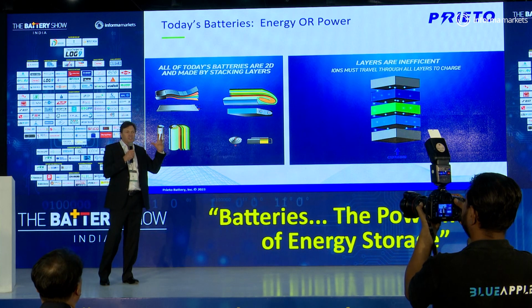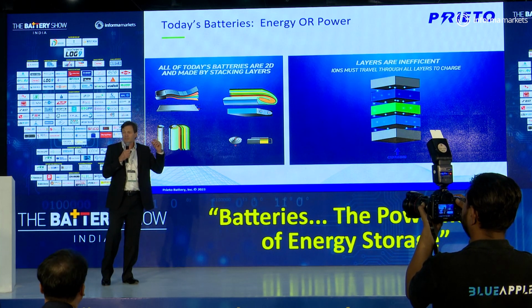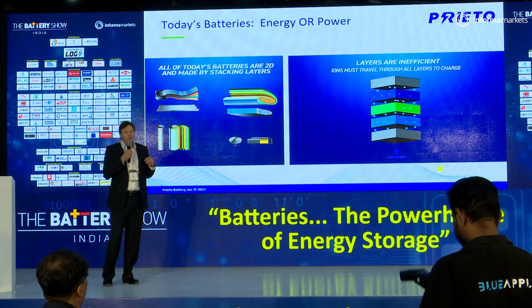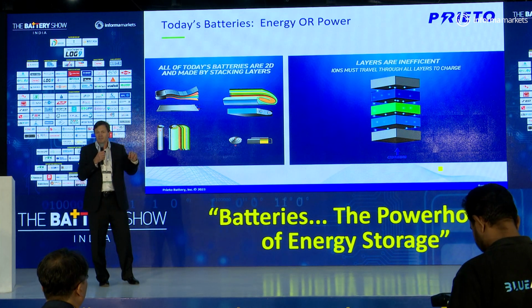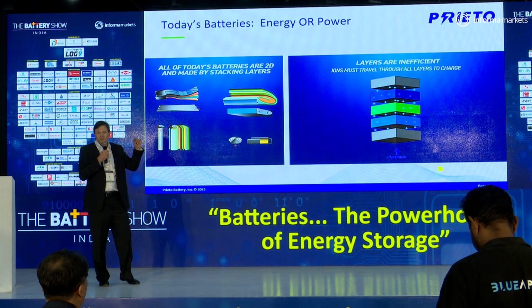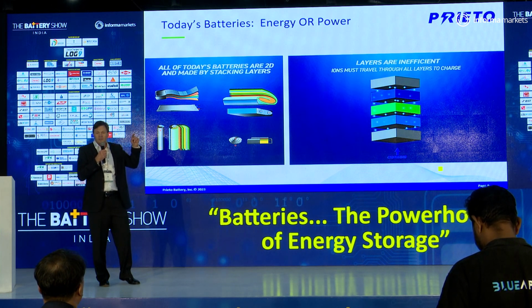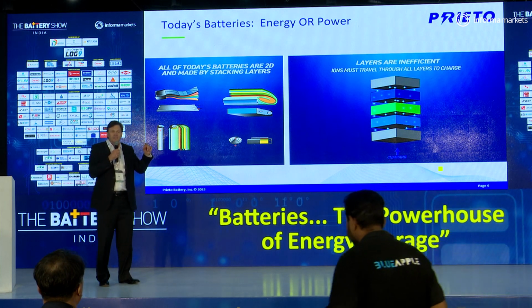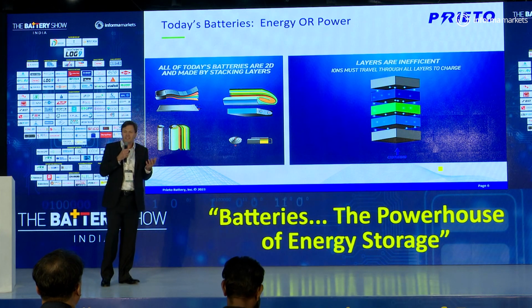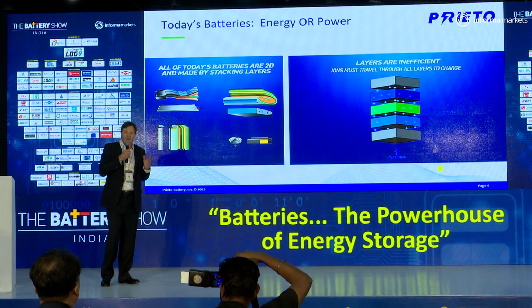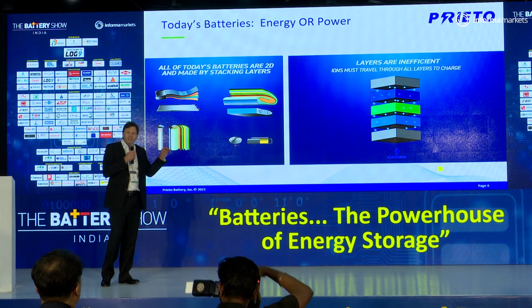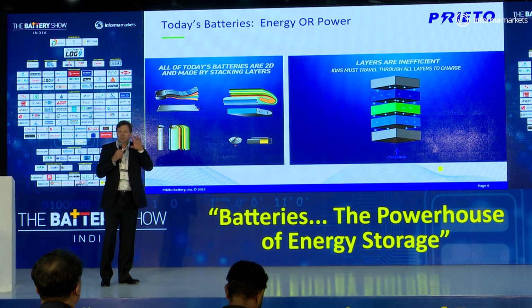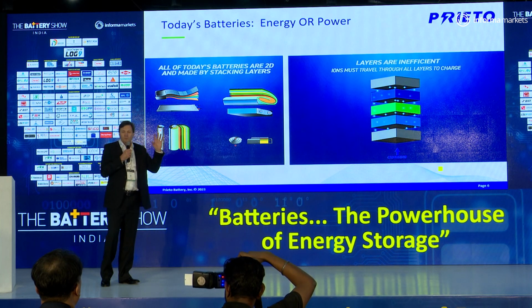So you have a very high energy density battery, but very slow charging and very low power output. If you want a fast charging battery, you make those layers very, very thin, so the lithium ion can go back and forth very quickly, but now you have no energy density. This has been a conundrum for battery designers for decades. How do you have a battery that has both high energy density and high power density, or fast charging, in the same battery? People are still trying to figure this out and trying to get that optimum balance. A 3D battery does both.